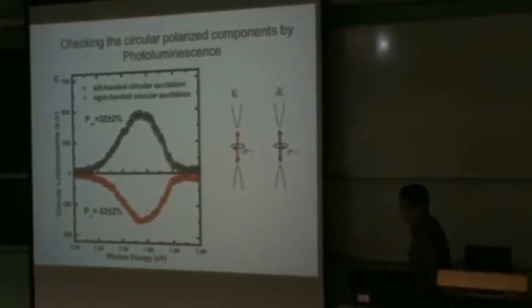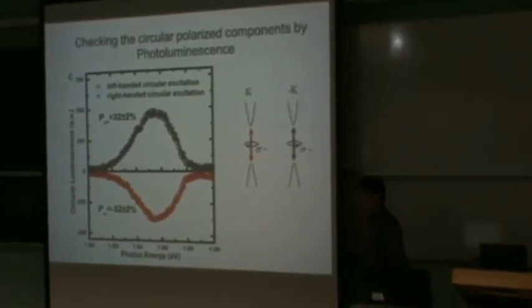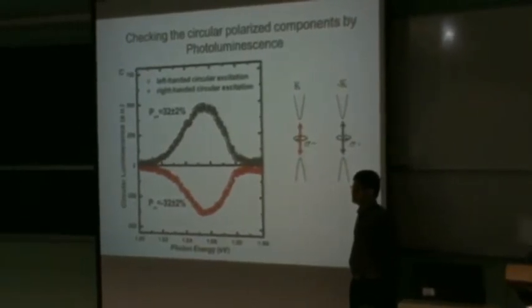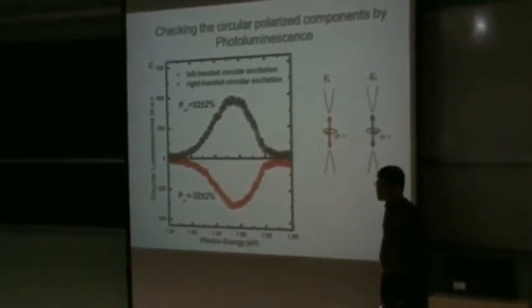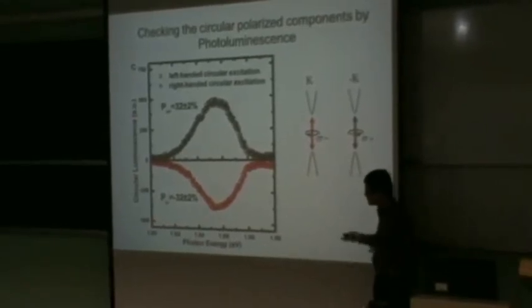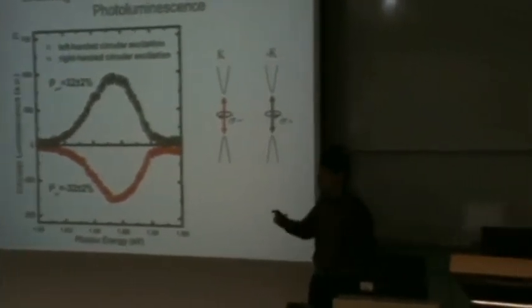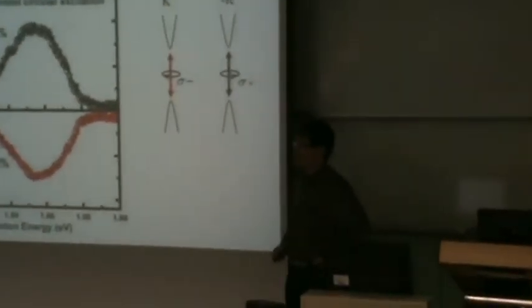And what about across the sample? This sample here is big compared to the spot size, or the sample is how big? The size ranges from a few microns to, at most, possibly less than 20 microns. What is the lifetime of the luminescence? For the monolayer, the lifetime we can observe from molybdenum disulfide is around a few hundred picoseconds. Generally 100 or 200 picoseconds.